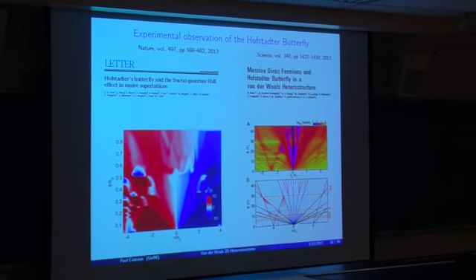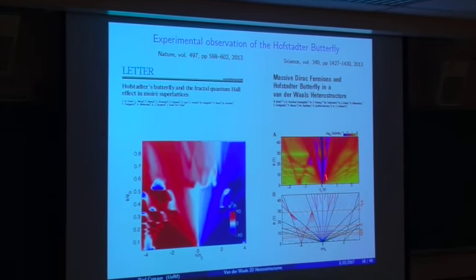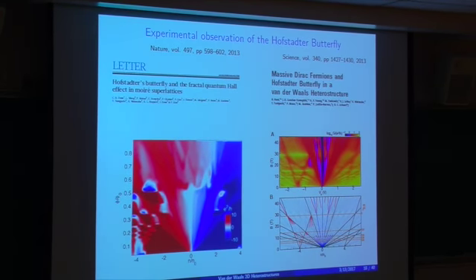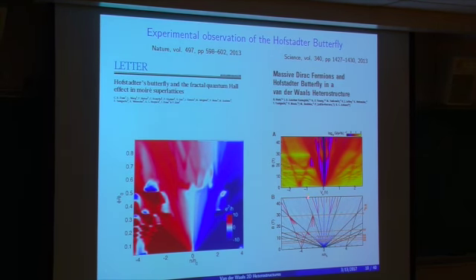So what we can see here in blue, tracing the rays that appear in the experimental results over here, are the fans, the Landau levels that will appear just in graphene itself. But then the red additional rays appear because we have here an integer value, for example, of the ratio of fluxes over here or here. These come from the repetition from this Hofstadter butterfly. So this was an interesting application of these heterostructures.